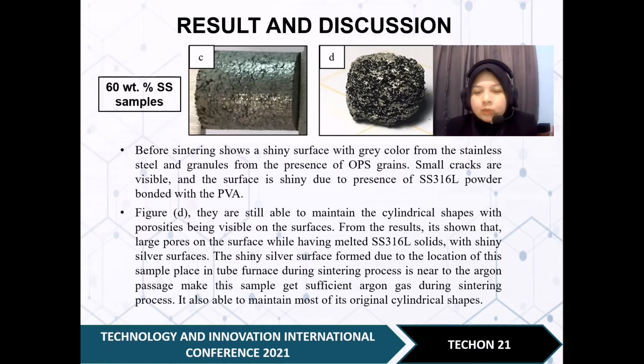Okay, next we increase the stainless steel content in the mixture to 60%. Same as the previous samples, figure C is before sintering and figure D is after sintering. Before sintering, it also has a shiny gray surface and a little crack happens here due to the different size between oil palm shells and stainless steel.